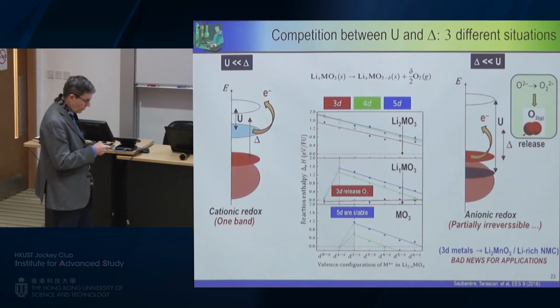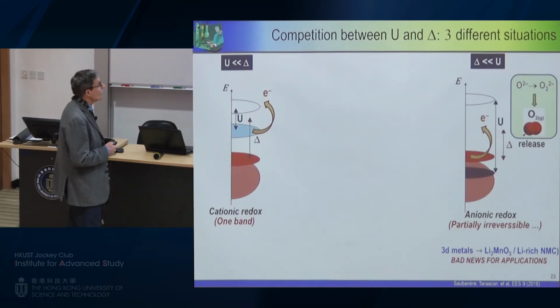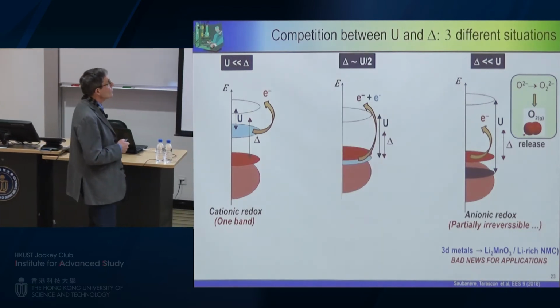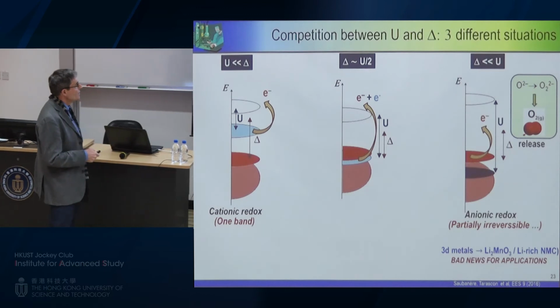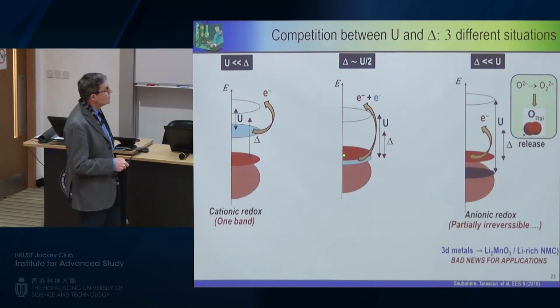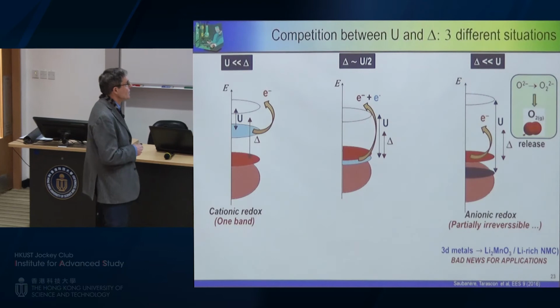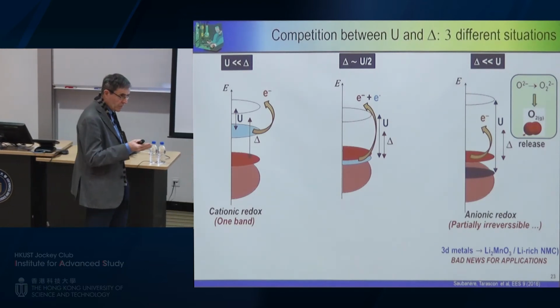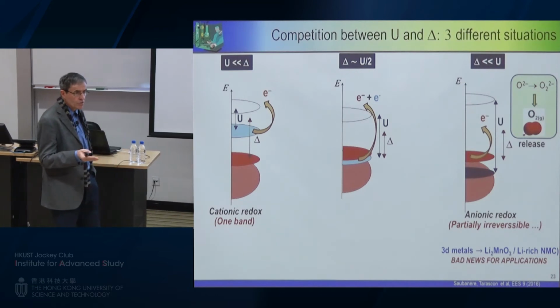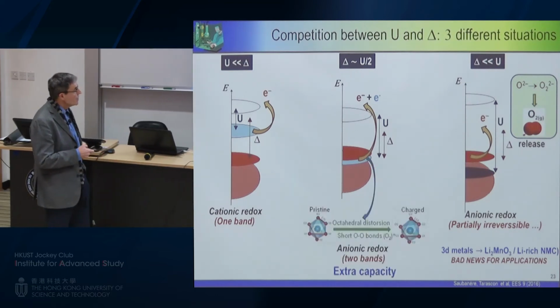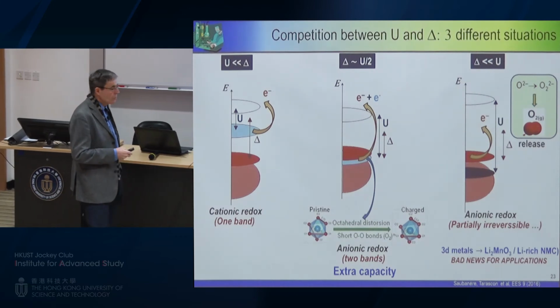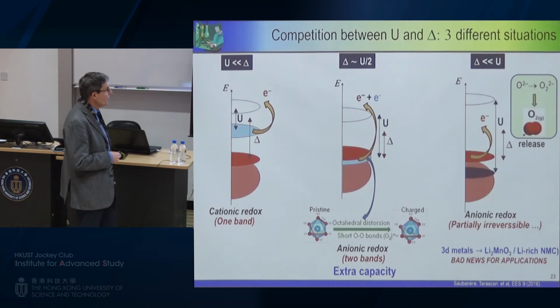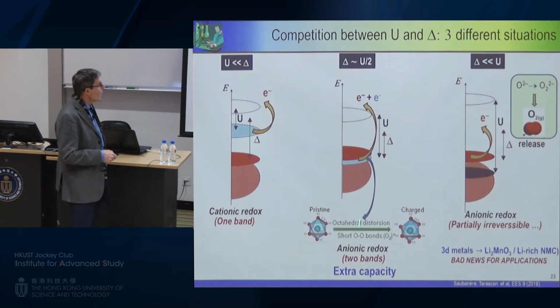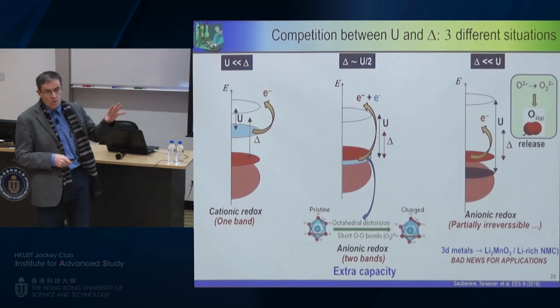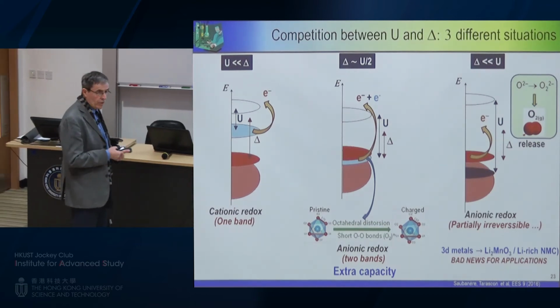Now, let's look at the most interesting case, in which the term delta is nearly U over 2. And in this case, you can see we have both at the Fermi level this non-bonding state plus this MO, molecular orbital antibonding, which means that we have two orbitals at the Fermi level. This is a very unstable situation, and you are going to lift the degeneracy by creating a distortion, as we have been observing in this compound. And here we have nearly the anionic redox with two bands, and we have this extra capacity. So I hope that you understand what is the origin of this anionic redox.